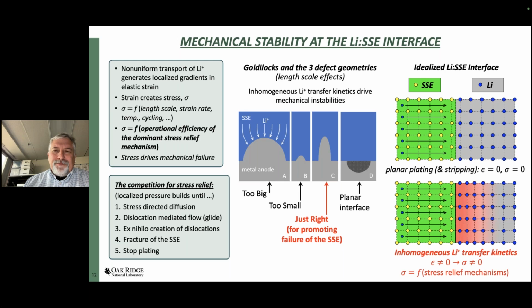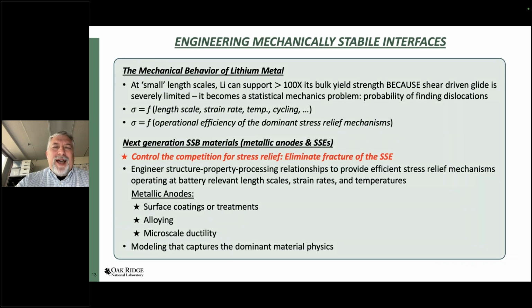All right, this is the last slide, and it's a summary that explains how we currently think about engineering mechanically stable interfaces in our solid-state batteries. As I hopefully have made very clear, the key issue is that the mechanical behavior of lithium changes radically at battery-relevant length scales. It can support more than 100 times its bulk yield strength when dislocation glide is inoperable.